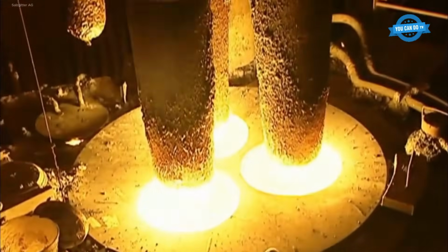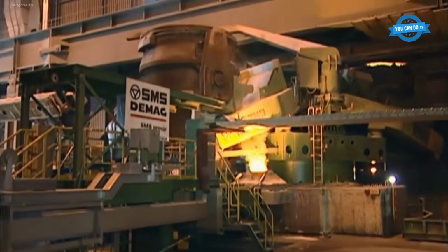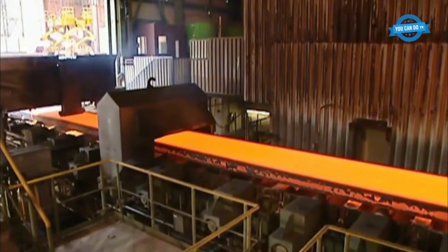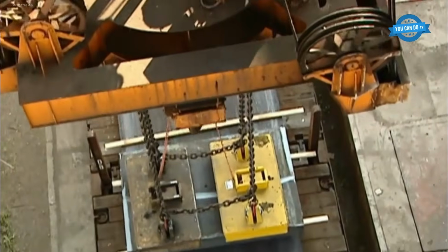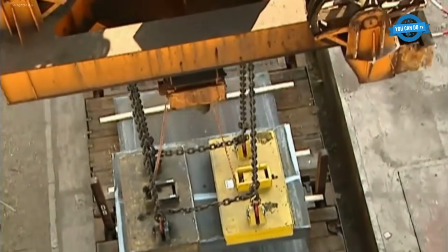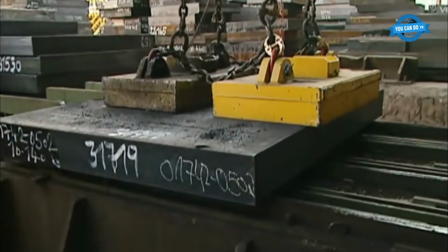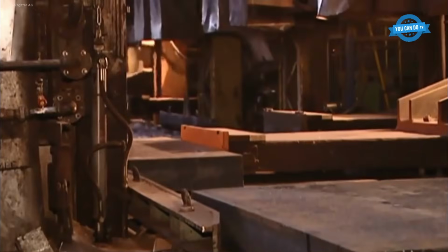The 2 by 6,400 kilowatts drive powers work rolls supported by backup rolls, achieving thickness tolerances of plus or minus 0.5 millimeters across widths of 800 to 3,500 millimeters.